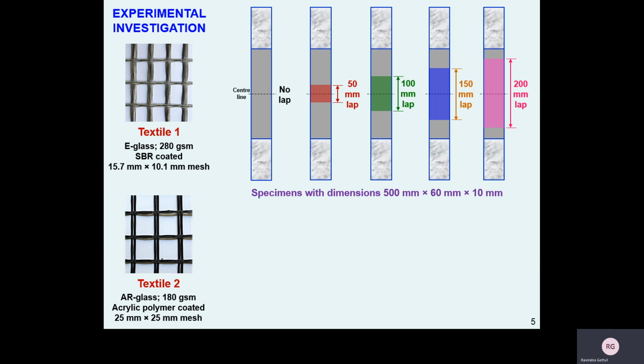The first type is SBR coated E-glass textile with 15.7 mm by 10.1 mm of mesh opening, and the second type is an acrylic polymer coated AR glass textile with a bigger mesh size of 25 square millimeters. With 7 specimens for each combination, 70 specimens were tested under tension in total.